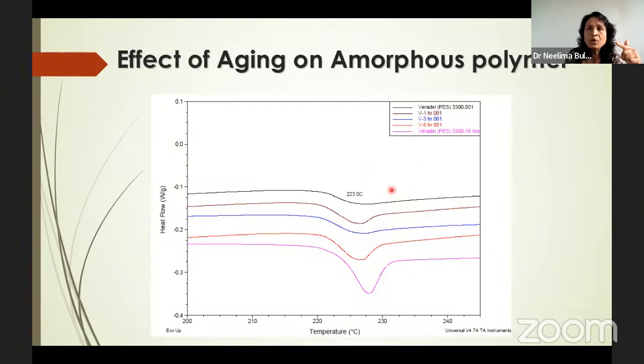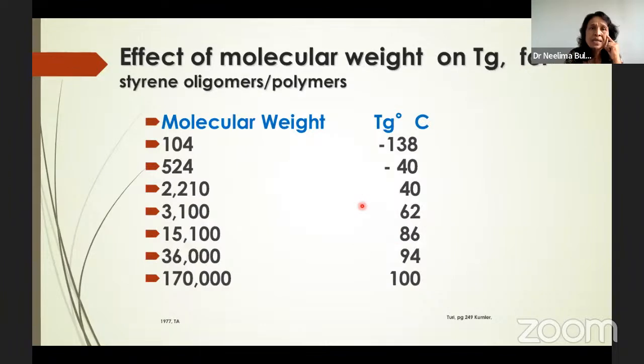Suppose you are using a polymer sample, which should give a curve like this black curve. But if you are getting a curve like the pink one in your DSC, it shows that your sample is aged because you kept it for a long time on a shelf. So don't use this sample, because the pink and black materials have different material properties. So aging affects the TG of your sample.